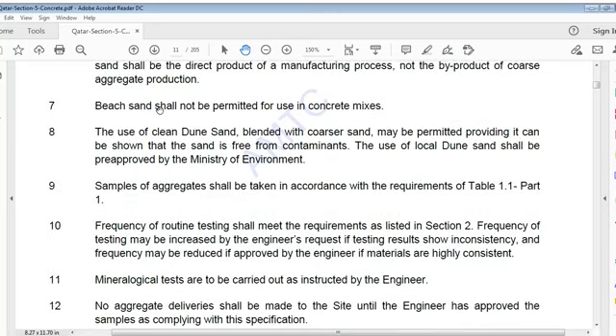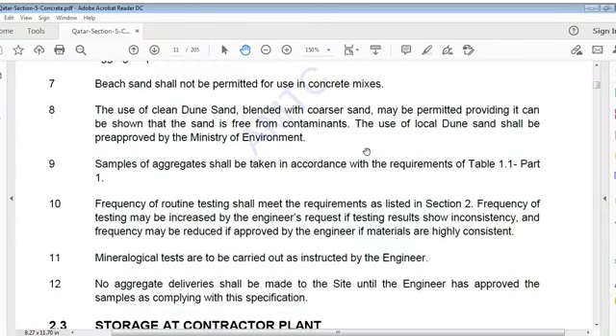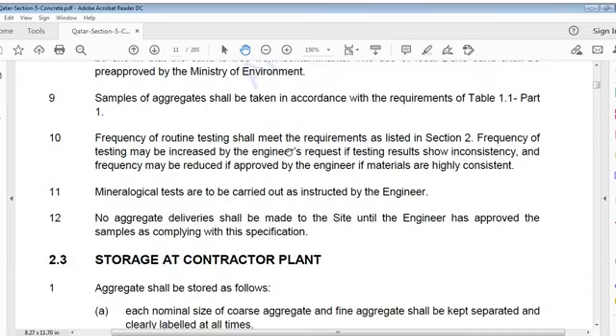Beach sand shall not be permitted for use in concrete mixes. Repeat, beach sand shall not be permitted for use in concrete mixes. Use of clean dune sand blended with coarser sand may be permitted, providing it can be shown that the sand is free from contaminants. Use of local dune sand shall be pre-approved by the Ministry of Environment.